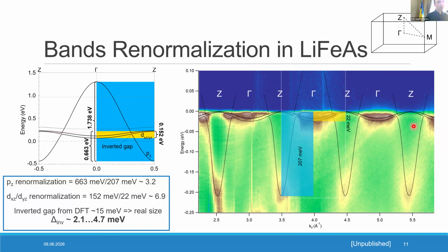From this comparison, we found out that renormalization was actually different for different orbitals. So the PZ band is renormalized by a factor of 3, while DXZ and DYZ is renormalized by a factor of 7. And therefore, as it is known, this spin-orbit induced hybridization also renormalizes the same way. Of course, we can't say for sure whether it will renormalize by the smallest factor or by the largest factor. So the rough estimate for the inverted gap in this case is something between these two values. Because in theory, it's predicted to be 15 meV, maybe 18 meV in some calculations, the real size is expected to be at least 2 meV, and the largest possible size is 5 meV. So it's quite big already, expected to be much bigger than in iron tellurium selenide. So it's already a good start.